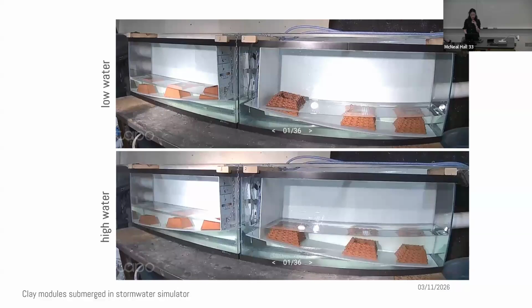So we currently have 2 fish tanks set up with pumps to fill and release water each week. We also have cameras for time-lapse setup for documentation, as you can see in this image, and a webcam so we can monitor the experiment from afar. We're currently running the first experiment on modules fired to 950 degrees, with 2 more coming scheduled to test 1100 and 1250 degrees firing temperature modules.